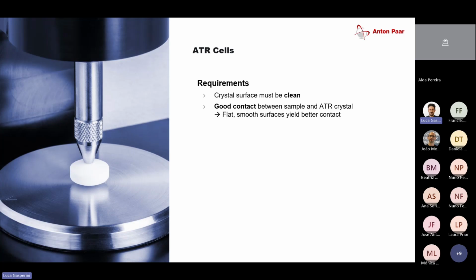Then for solid samples, it's very important that the contact is very firm. You want to make sure that you apply a lot of pressure onto the sample, so that the sample covers the full part of the crystal. Otherwise, you will not get as much intensity.